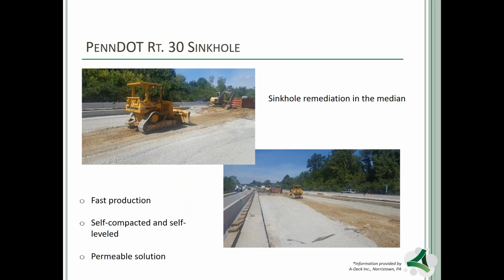I've got to tell you about an interesting project that we observed after the placement of pervious cellular material on a sinkhole in Pennsylvania. When we showed up 72 hours after the placement, we saw tracked equipment going directly over the pervious cellular material. Obviously there was some scarification, but it was very much on the surface and really became a non-issue. So we were happy to see that in such a short period of time.